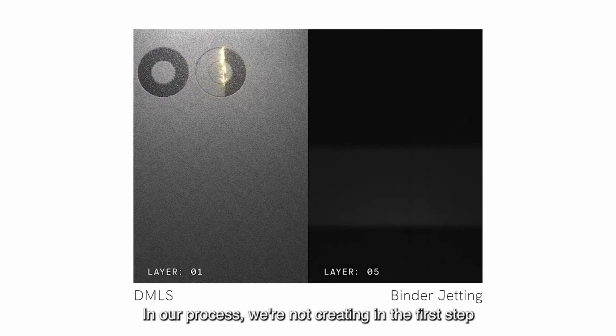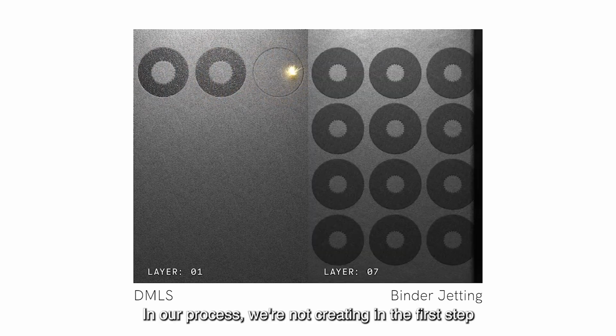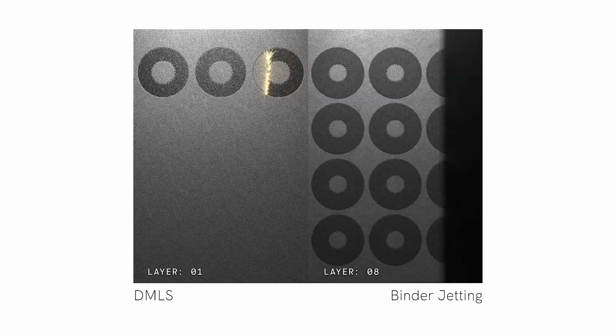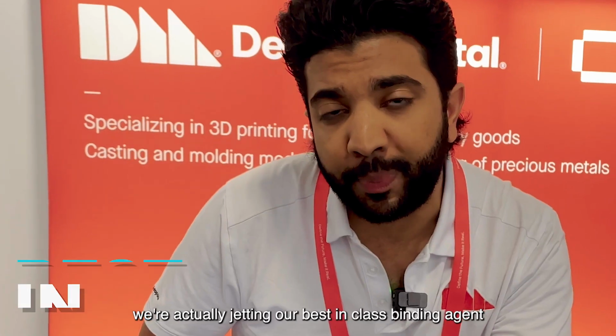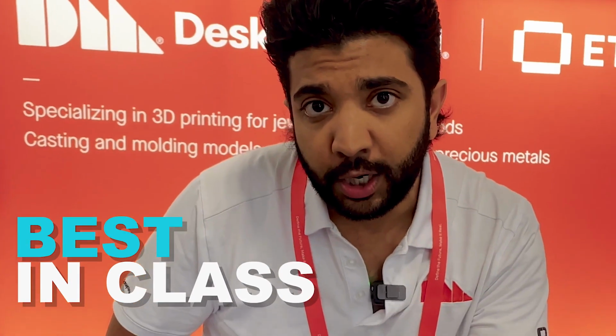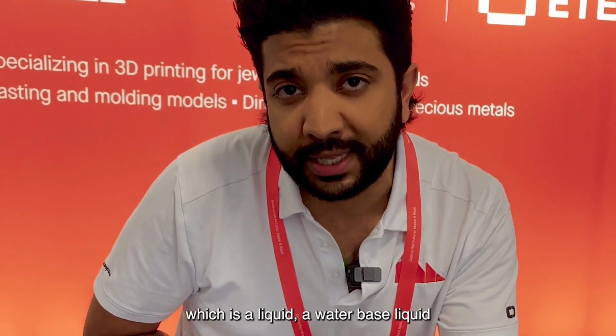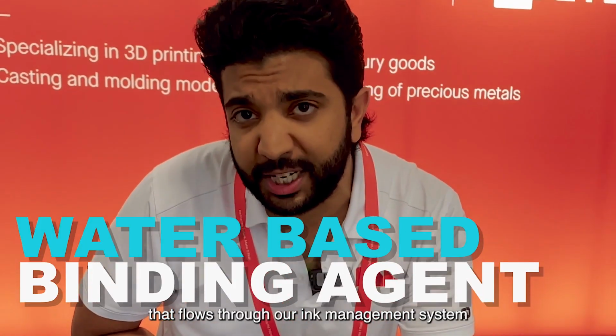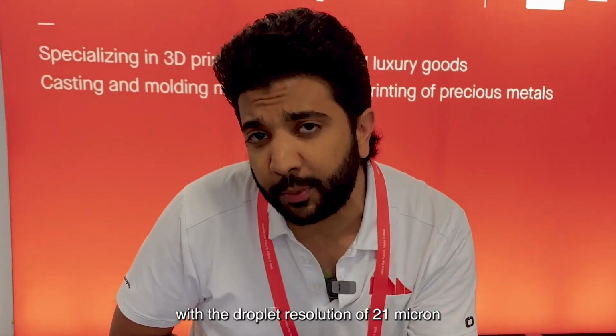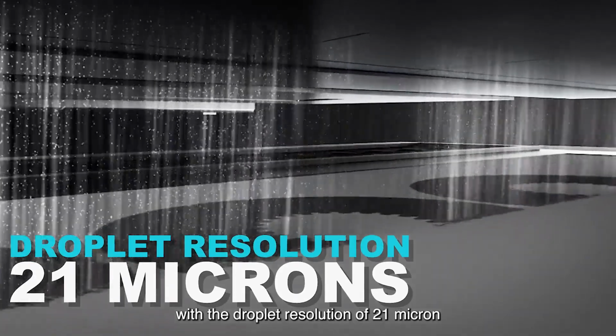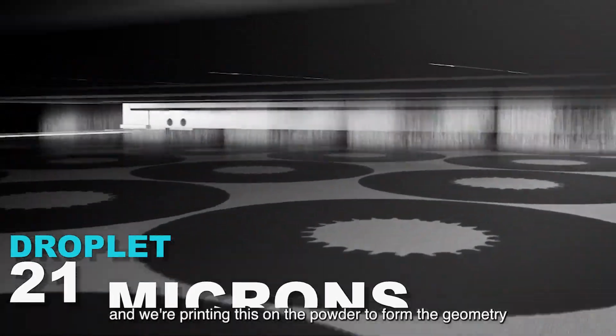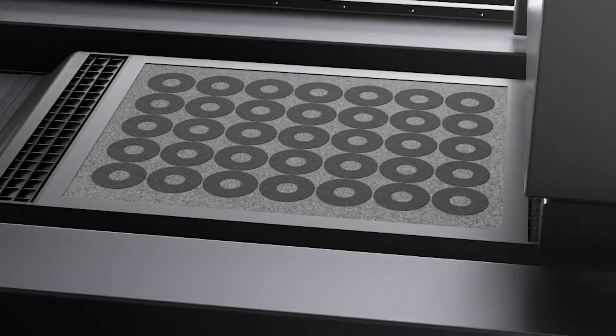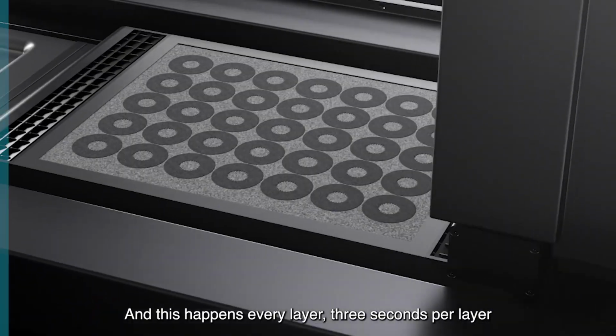In our process, we're not creating a solid metal part in the first step. We're actually jetting our best-in-class binding agent, a water-based liquid that flows through our ink management system with a droplet resolution of 21 micron, and we're printing this on the powder to form the geometry. And this happens every layer, 3 seconds per layer.